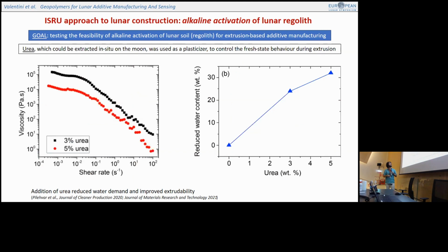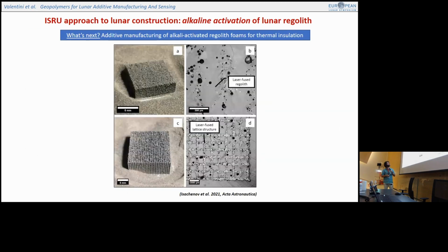Okay, so here you can see some results from rotational rheometry, in which again we see that the viscosity is reduced as the amount of urea is increased. And again, also on the left, we can see how the demand of water is reduced proportional to the amount of urea. Okay, this result was published in a couple of papers. And the next step is that of moving towards foamed materials.